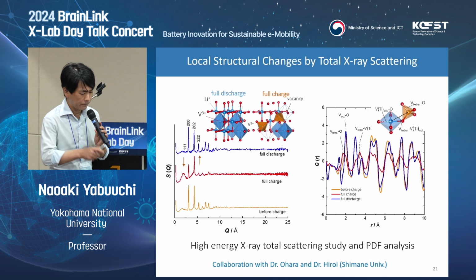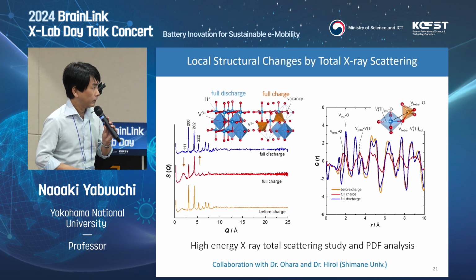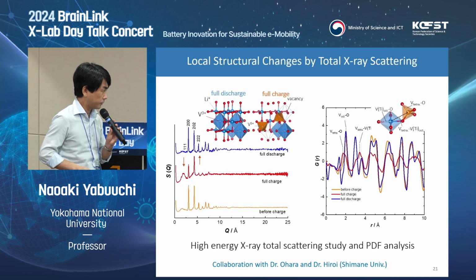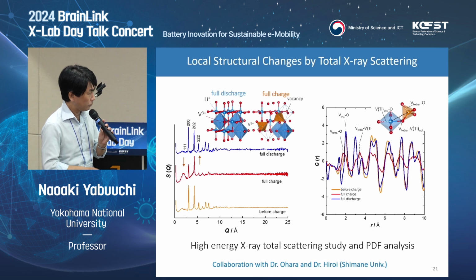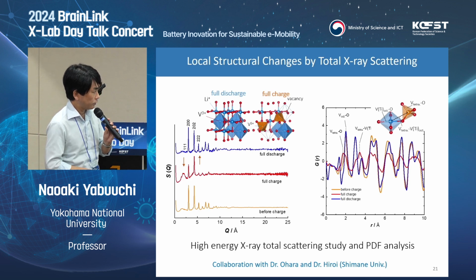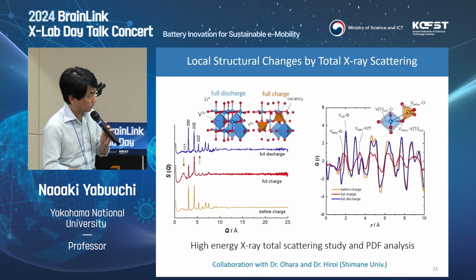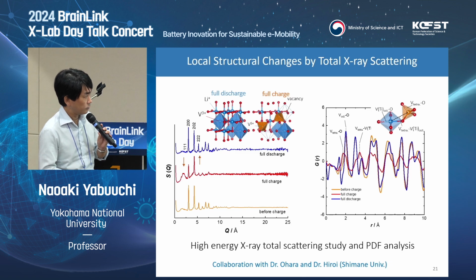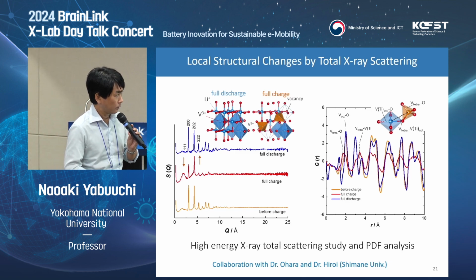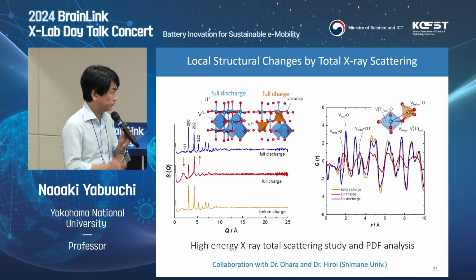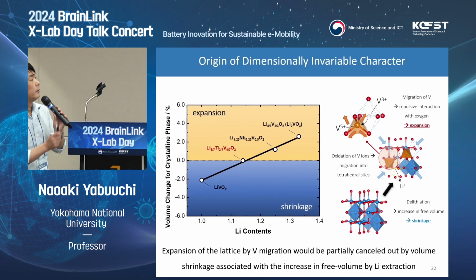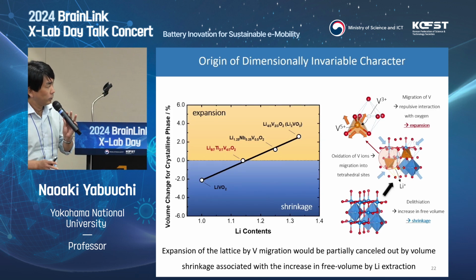So vanadium ions are very small and migrate to small tetrahedral sites. However, this migration process is reversible upon discharging. Vanadium ions migrate back to octahedral sites. A similar trend is observed for the PDF data. So why do we have a zero volume change character?